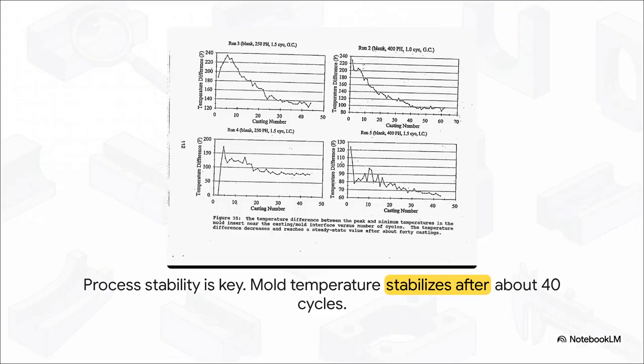Now this is really cool. Take a look at this graph. It shows us everything about consistency. See how for the first, say, 30 or 40 cycles, the process is all over the map while the die heats up, but then it settles down, it finds a rhythm, it gets stable and predictable. Your job as an operator is to get your process into that stable window as fast as possible, and then keep it there. That's where you make perfect, defect-free parts every single time.